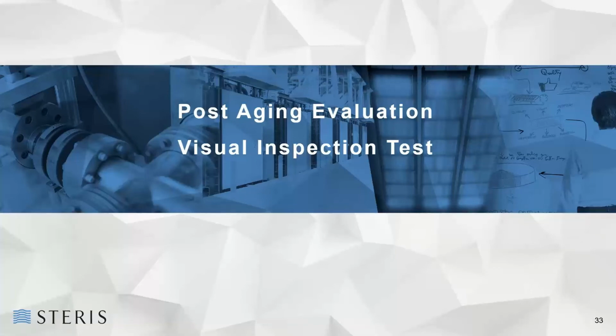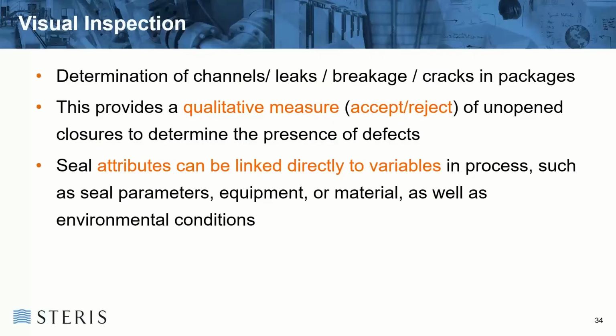If you look at, say, the likes of the post-evaluation testing, what can you do? The typical one that's done by most companies will be the likes of the visual inspection, typically to ASTM F1886. Basically, what you can do here is determine channels, leaks, breaks, cracks, melted product, melted packaging, product that's come out of its place. It's a qualitative measure which gives you an accept reject rate of the unopened packaging. It gives you an attribute that can be linked directly to variables in your process, such as the seal parameters, the equipment that's been used, the material that's been in the product and the packaging, as well as the environmental conditions that it's been exposed to, whether it's been underexposed or overexposed.